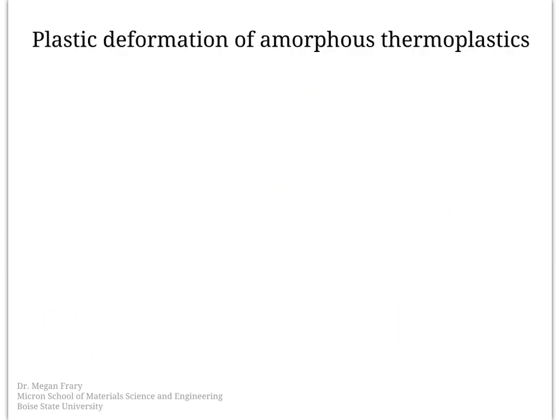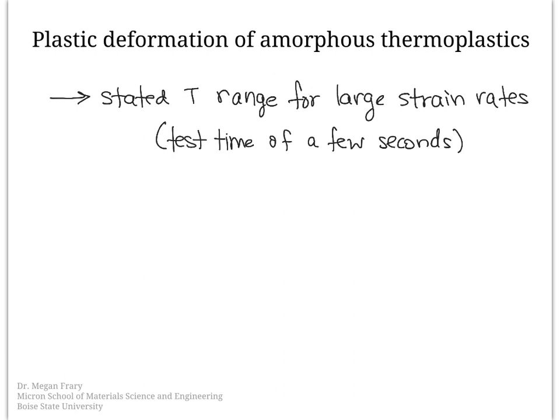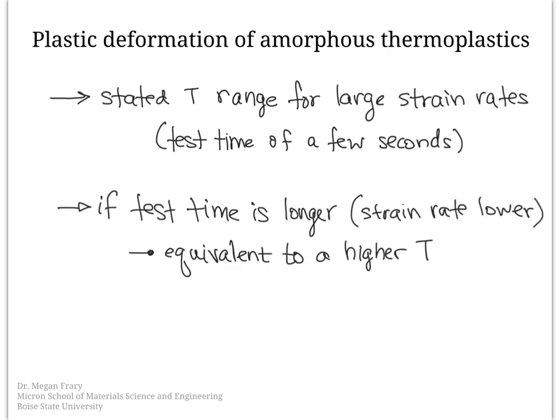For amorphous thermoplastics we're going to go through several different temperature ranges. One important note is that the stated temperature regions are for a rather large strain rate, so a testing time of just a few seconds. If the test time is longer, the strain rate is slower, which is equivalent to shifting the temperature upward. As with all high temperature plastic deformation, the strain rate and temperature are interconnected in determining the behavior.